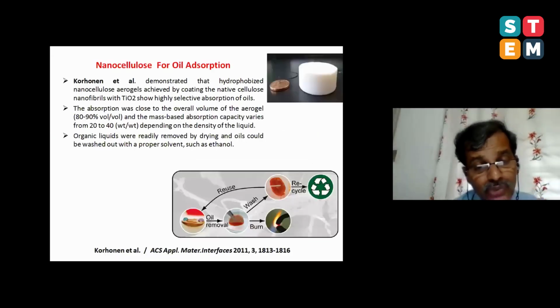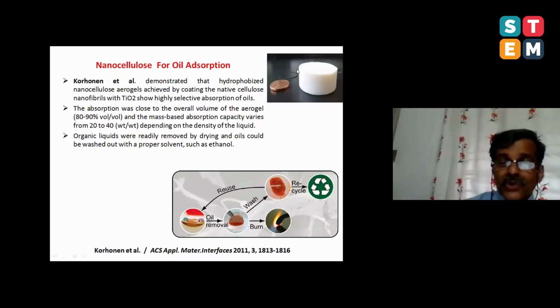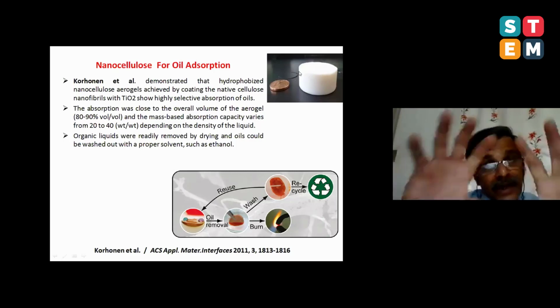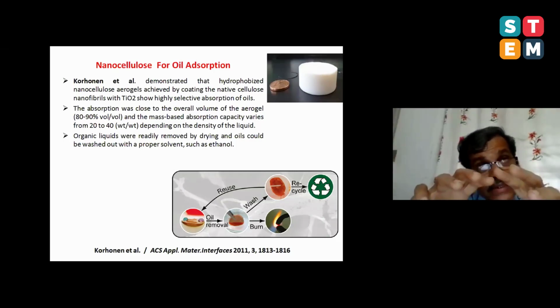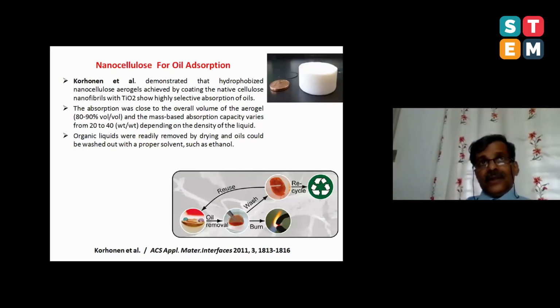I also wanted to show you some nice work of the Korhonen group in Finland. What they did is, they made aerogels out of nanocellulose made from waste. Look at the aerogels made by the Korhonen group. Look at this aerogel. And this aerogel has been chemically modified to make it hydrophobic. Essentially, cellulose aerogels are hydrophilic because cellulose is hydrophilic. What they did is, they made a titanium dioxide treatment on the surface of the aerogel. As a result of this, the aerogel became hydrophobic. And this hydrophobic aerogel is able to remove oil from contaminated water. The water is contaminated by oil.